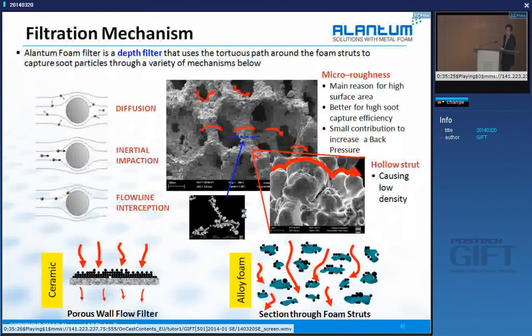For nanoscale or very fine particles, we have a diffusion mechanism, just going through and diffusing in. And for the big particles, tens of microns in size, they just impact. That's the so-called inertial impaction. Then the particles in between do flow line interception. You can see this three-dimensionally tortuous path. Going through, most of the soot or particles get collected on top of these areas.